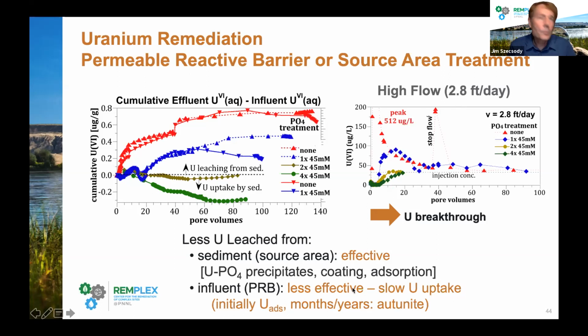That's primarily because the processes of uranium uptake are slow. And if you're flowing groundwater pretty fast, the uranium flux rate through that system is faster than the uranium uptake rate by the phosphate phases.